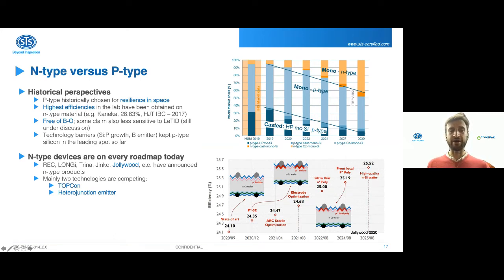But somehow N-type had up to now some technology barriers that were difficult to overcome. The boron emitter growth or diffusion is a problem with the boron skin. The growth of phosphorus silicon is also an issue. So it is a little bit more difficult to do N-type, and that's one of the reasons why it's not the dominating technology today.